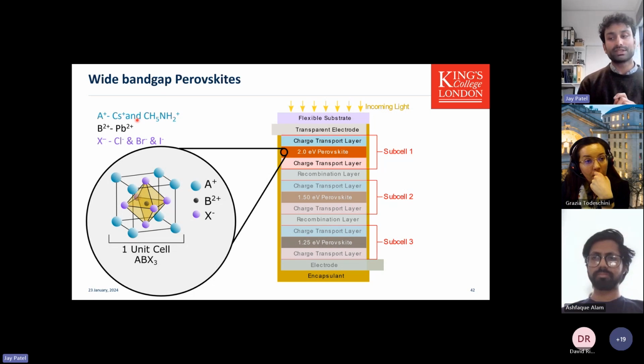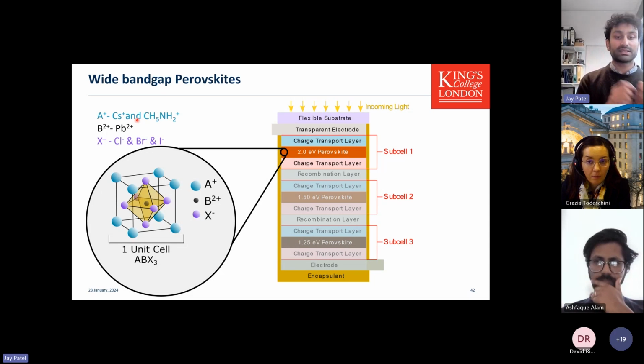Another thing to note, which is key, is in multi-junction devices, when you go roll to roll using solvents, you need solvent orthogonality. So when you have so many different layers, you need to make sure if you deposit the perovskite with an X solvent, that X solvent doesn't interact with the preceding layer and dissolve it. Now, you completely mitigate that with PVD. And so with PVD, you don't have to worry about that. There is no infiltration and damaging of the preceding layer when it comes to manufacturing.